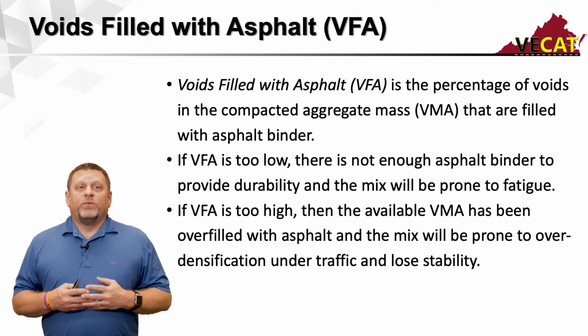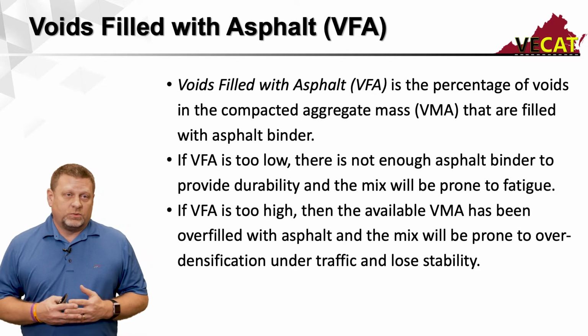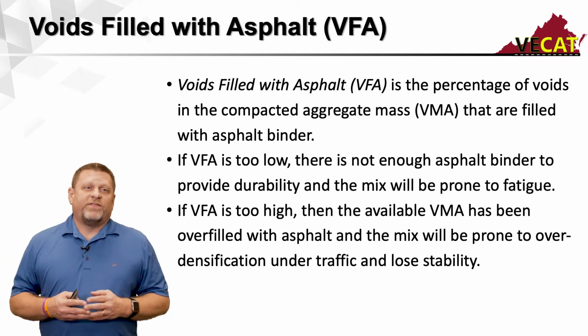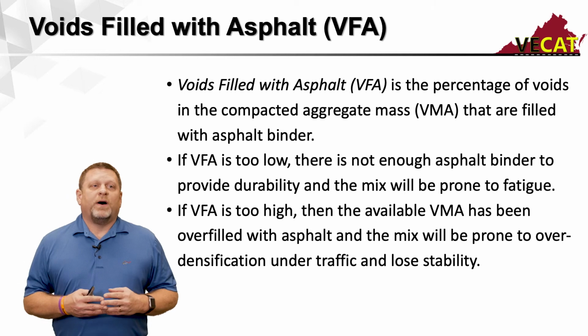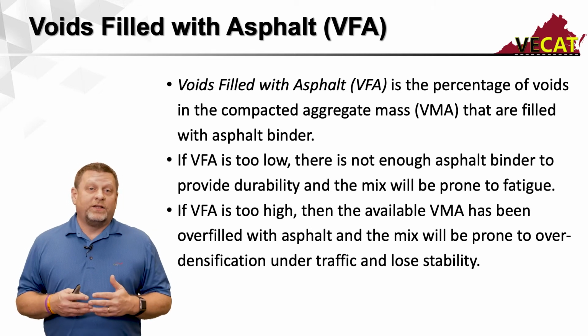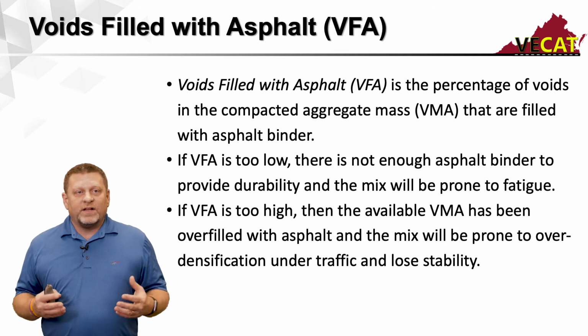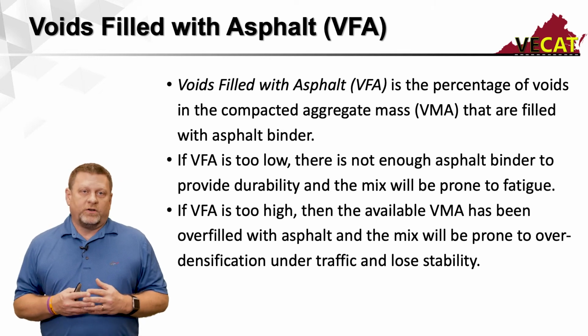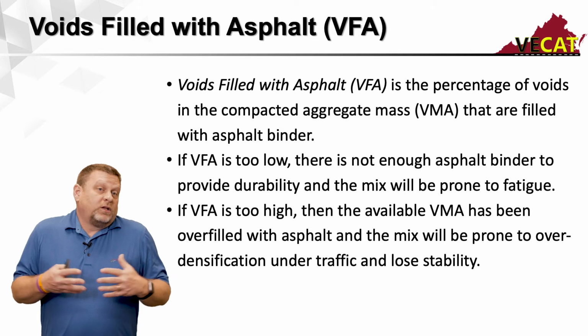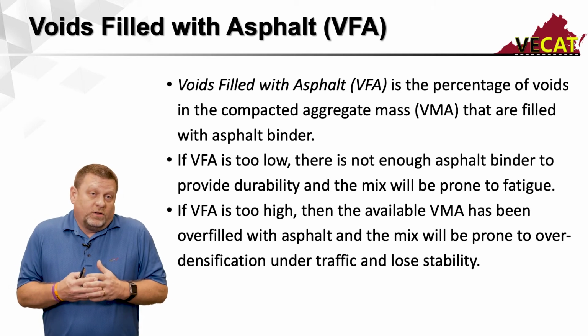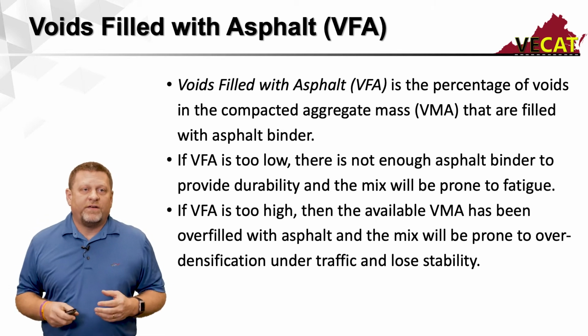You got to be careful with your VFA. You can have too much of this as well. If the VFA is too low, there's not enough asphalt binder to provide durability, and basically your mix is going to be prone to fatigue, prone to raveling, prone to things that it isn't going to hold together as well. Again, if you don't have enough binder to glue everything together, it isn't going to have enough glue to hold together. So you got to make sure you got enough of that.